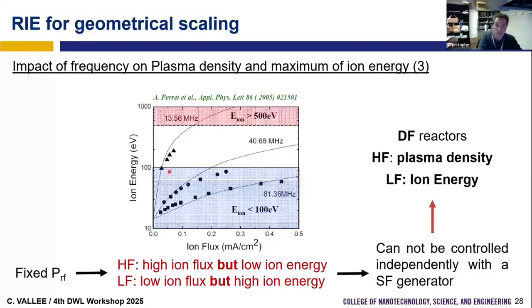But if we use a low frequency generator, so in this case, the low frequency is 13 compared to 81. If you use a low frequency generator, the ion flux will be less, the plasma is less dense, but since we have less current flowing to the substrate, we develop more voltage, more peak to peak, so we develop more VDC, so we have more energetic ions. So we see that we have opposite behavior of the frequency for the flux and the energy. But if you have a single frequency generator, you cannot decouple.